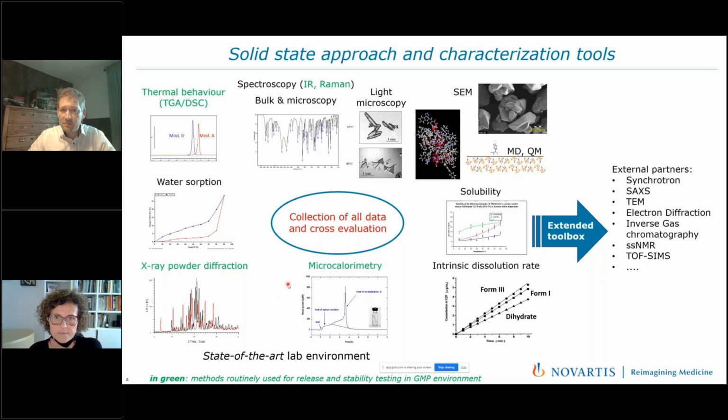We are applying spectroscopic techniques, mainly mid-infrared and Raman spectroscopy, in bulk or in microscopy modes. We also have light microscopy, together with scanning electron microscopy. But we also use quantum mechanics and molecular modeling in order to understand what will happen to our drug substance. Certainly, we are able to characterize them by solubility and dissolution kinetics. And in case we are interested in crystalline content, we may use microcalorimetry.